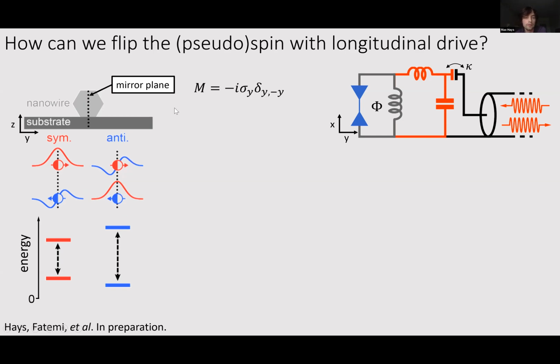And so if this mirror symmetry operator is preserved, then we're not going to be able to drive the spin flipping transitions between the doublets. But in our system, oh yeah, and sorry, this can also in principle be mixed by the second transverse Rashba term. So here, the sigma y dx, this is the term that was giving us one of the spin orbit effects we need in our system, and then there's this transverse Rashba term as well that is going to mix between these various subbands and spin states.